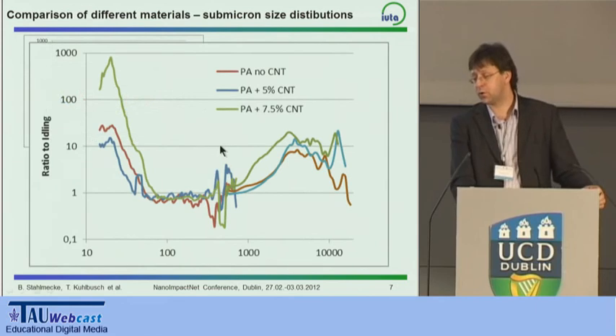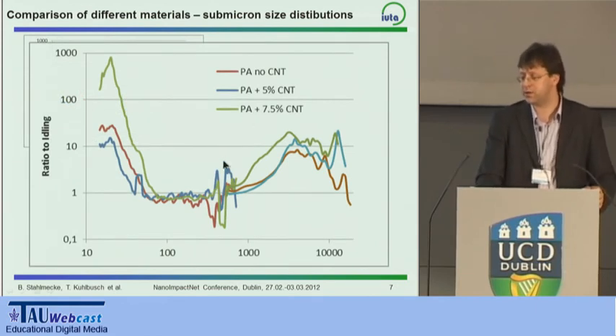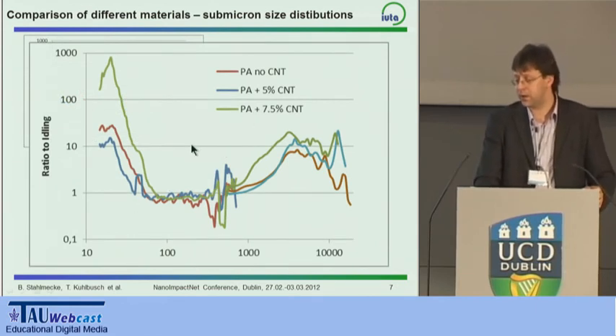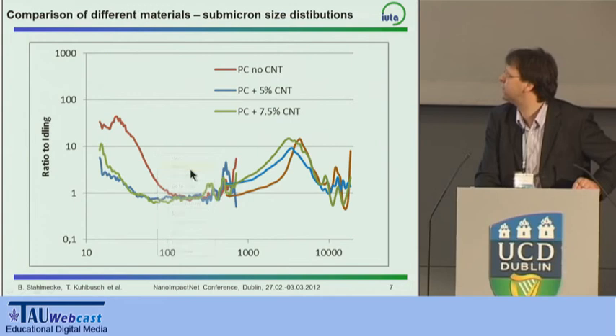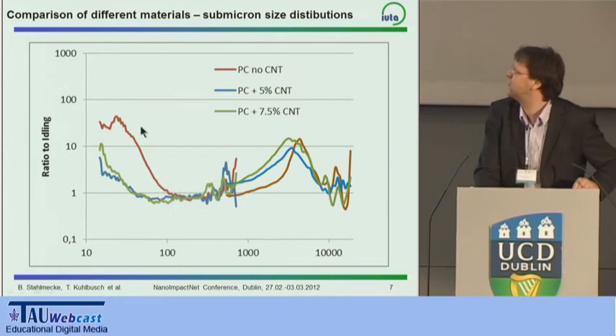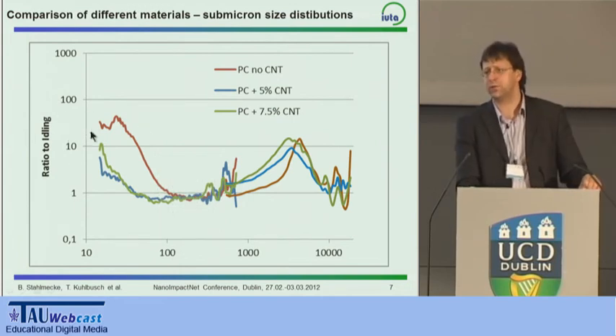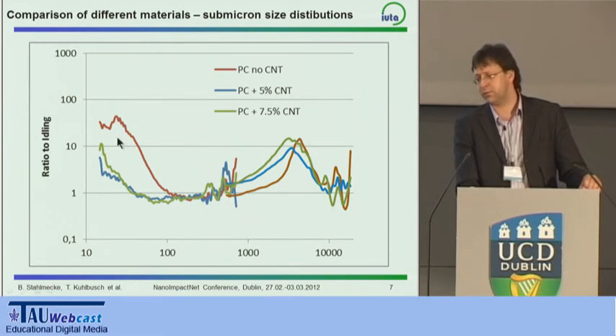If we go from the polycarbonate to the polyamide, we have a similar picture. Sorry, I forgot one thing, going back to the previous slide. What is interesting here is that we have the highest emission of sub-micrometer particle number concentration within the polycarbonate for the material where we have no CNT added to it.